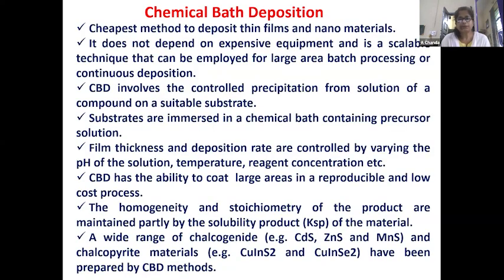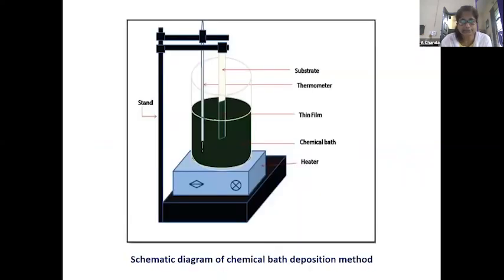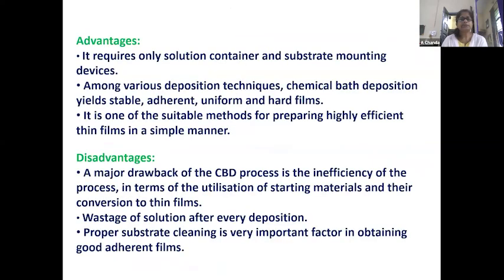Substrates are immersed in a chemical bath containing precursor solution. Film thickness and deposition rate are controlled by varying the pH of the solution, temperature, reagent concentration, etc. CBD has the ability to coat large areas in a reproducible and low-cost process. A wide range of chalcogenide and chalcopyrite materials have been prepared by the CBD technique. And the advantage is that it only requires the solution container and substrate mounting devices. It yields stable, adherent, uniform, and hard films. It is one of the suitable methods for preparing highly efficient thin films in a simple manner.